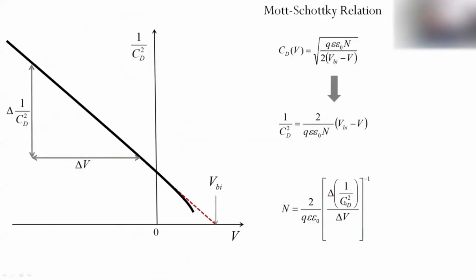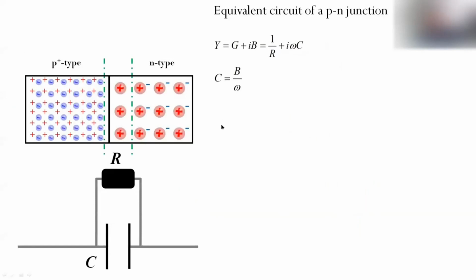Since this capacitance-voltage dependence of a PN junction is a very important parameter, we can use it in the Mott-Schottky relationship to plot 1 over depletion capacitance squared versus applied voltage. From the intersection of this linear dependence with the voltage axis, we define the built-in voltage, the height of the potential barrier, and from the slope of this dependence, we can determine the concentration of doping. It's an important parameter to characterize semiconductors which we use in our research or in making devices. So in order to use this Mott-Schottky relation, we need to operate with the capacitance of the depletion layer.